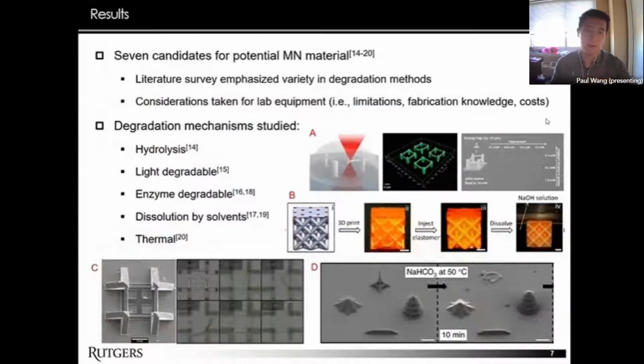So after looking through a ton of different papers, I found 7 materials that look promising. These were selected based on their degradation methods and also took into account our lab's fabrication equipment, such as whether we have the equipment to fabricate the material and if we have the knowledge of the process to fabricate it. A variety of degradation triggers is important. The mechanism determines how easy some materials are to degrade and how easy the degradation occurs. For example, a material that degrades under exposure to heat is difficult to fabricate because the process is time consuming and it can't be 3D printed as well. But the trigger, which is heat in this case, is extremely easy to use.